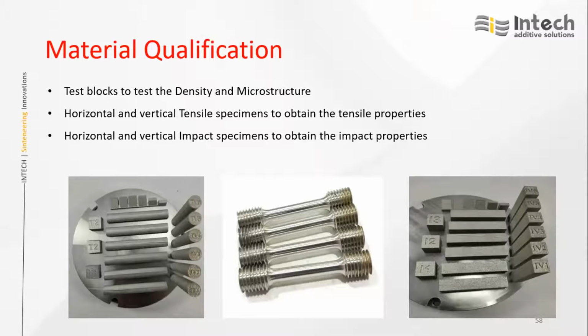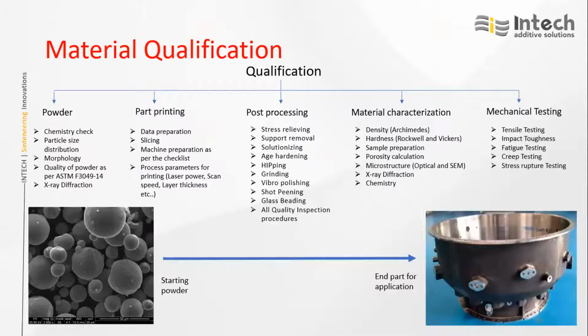On the right side image you can see angular plates, to get roughness optimization we need to print those kind of parts. These impact and tensile bars are in terms of cylinders or cuboid structures. This needs to be machined as per standards like ASTM E8 for tensile and E23 for impact, to the dimensions we need to machine, test, and qualify it.